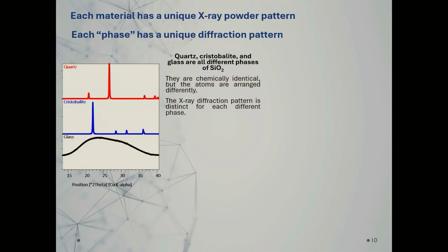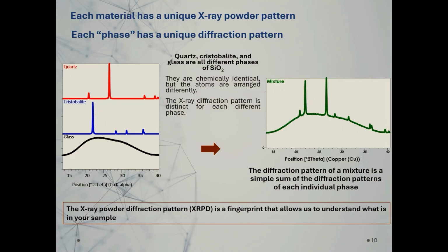So here is an example of 3 phases, or 2 crystalline phases. Each material has its own fingerprint powder diffraction pattern, so it has a unique X-ray powder pattern. These are the 3 cases that Rosanna already has shown: the case of quartz, cristobalite, and glass. As we know, the content of these phases is just silicon oxide. But if we look at the powder diffraction patterns, we have 3 really different cases. We have the case of quartz, the case of cristobalite, and the amorphous with this hill that is characteristic of an amorphous compound. So if we have a mixture of 3 phases, in the pattern we will see the sum of each diffraction contribution.